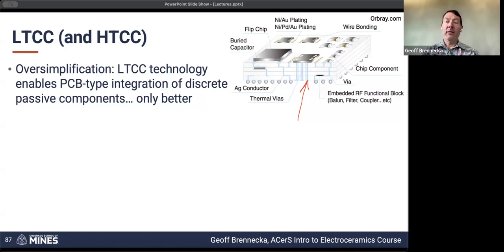So 750-ish. Sometimes, I guess the early ones were 900. Some of them have come down since then. The classics are still centered around 900. But from that, you can actually bury silver conductors inside of these. Some of them have been extended to copper and nickel and a bunch of other metals as well. The point is that we can take the same kinds of tape casting, stacking, lamination, cartoon that I walked through for MLCCs, and now do this with other materials and get drastically new capabilities that are integrated into a final component that's co-fired.